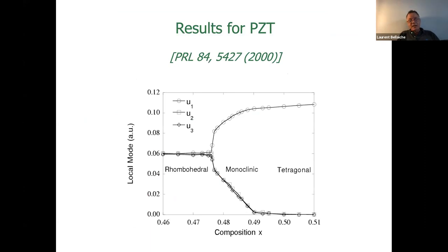So this came directly out of the implementation of this alloy effective Hamiltonian. This is the local mode, which means polarization versus composition. You see on the left side for smaller composition X, you have a rhombohedral state, polarization along 111. On the right side, for composition over 50% of titanium, you have a tetragonal state with polarization along 001, and in between you have something new. You have a monoclinic state for which the polarization is rotating between 111 and 001, and it's exactly the state that Beatriz Noheda was seeing one year before, in 1999.